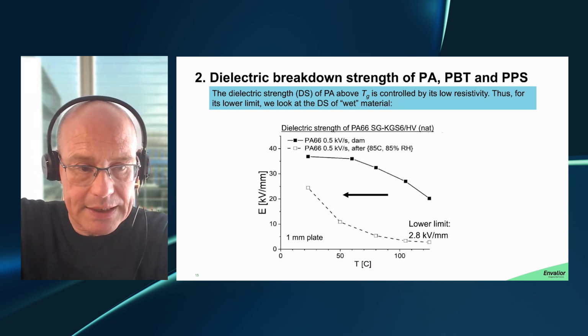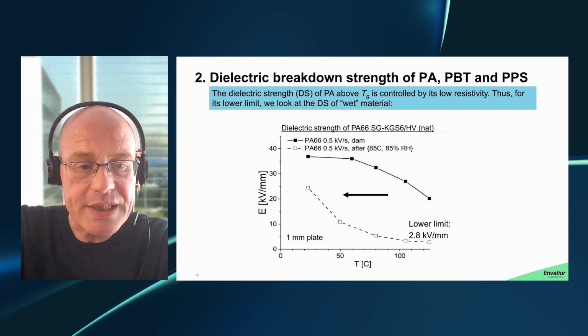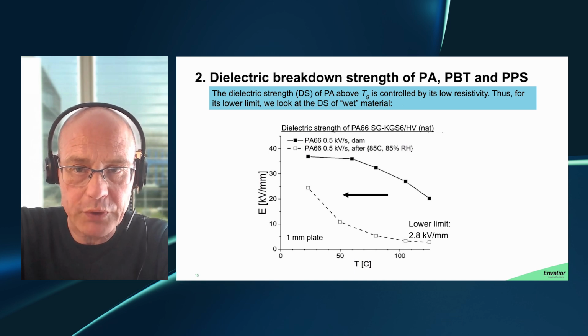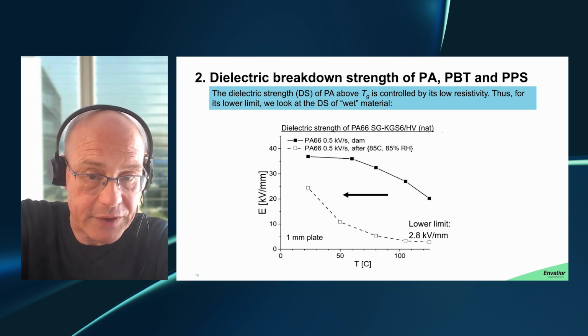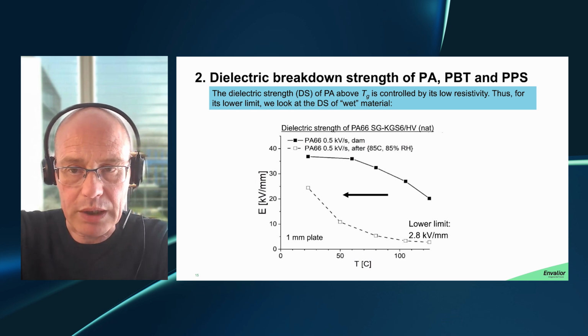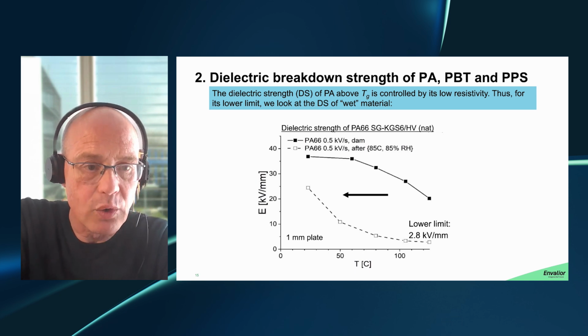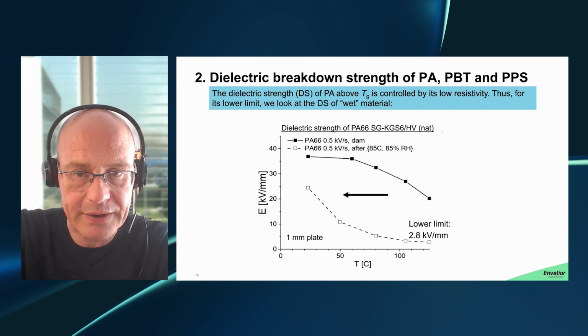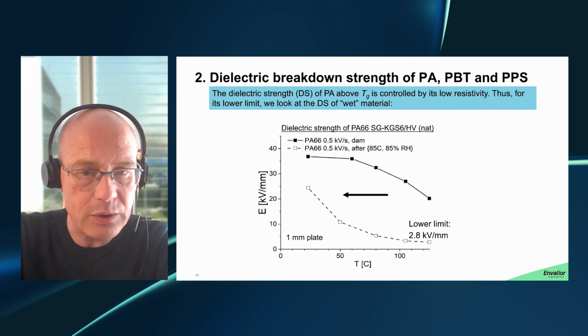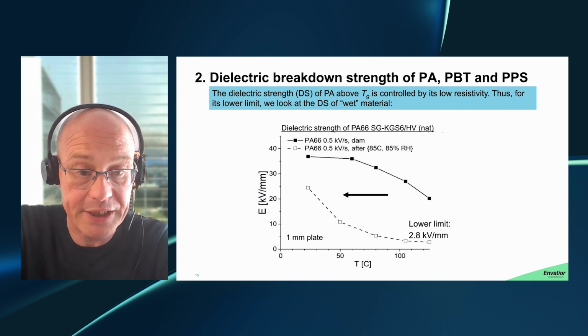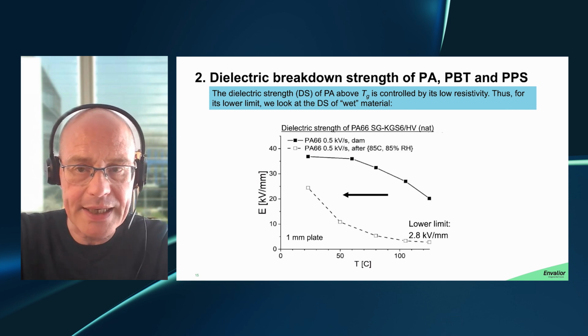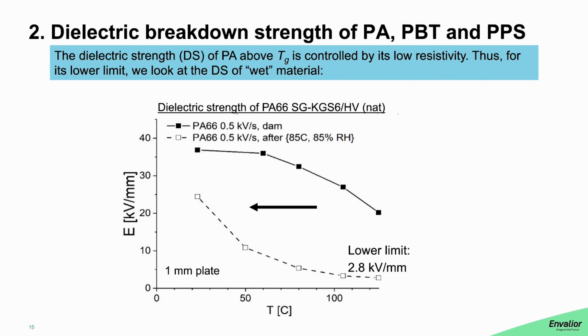Now, having established that the resistivity of the material is responsible for the breakdown of the material at high enough temperatures above the TG, one would like to know the, let's say, lower limit of the breakdown strength of such a material. And for that, we looked at wet polyamide 6,6, for which the resistivity is lowest. That is basically indicated in the dotted line in this particular picture. The full line is for dry material, the dotted line is for wet material.